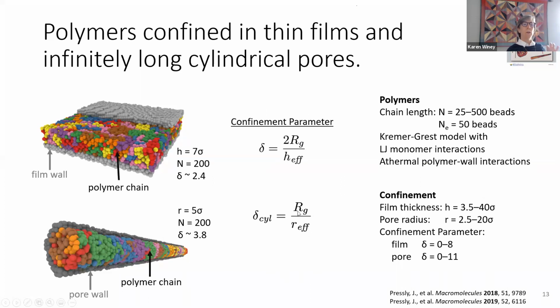In the case of cylinders, it's the radius of gyration of the polymer normalized by the effective radius of the cylinder. We used a range of beads per chain, and the entanglement length is just 50 beads, and a range of thicknesses and radii so that we have a wide range of confinement from like 0 to about 10 in both geometries. All right, so these were the simulations that James Presley did, and he was co-advised by Rob Riegelman at Penn.